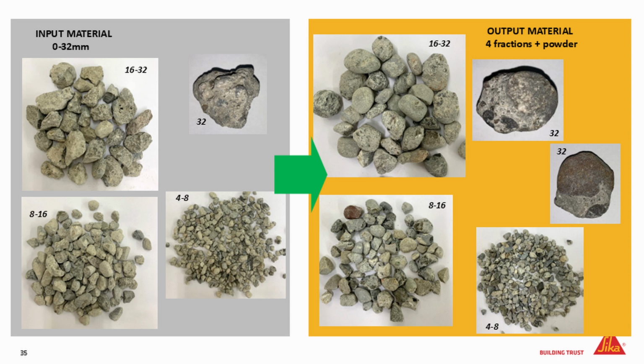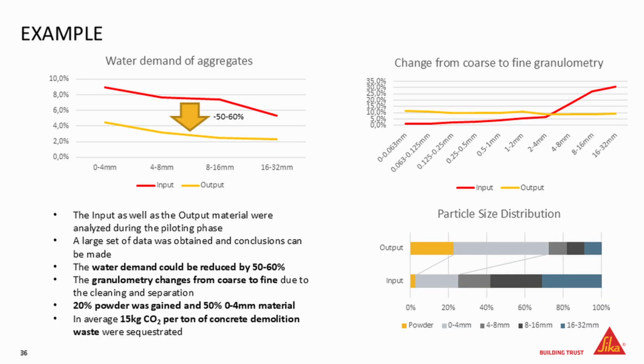What we measured all the time is the water demand. On the top left, you see the water demand of the aggregates, again, from small fractions to large fractions, and the red line is the input material that we take and measure the water demand. We basically measure the water absorption of the aggregates after 24 hours. This is what we do. You take the aggregates, you dry them, you put them into water, you surface dry them, and you measure the difference in weight. That we do with the input material, and with the output material of all batches, and then after 2 years we get some average values.